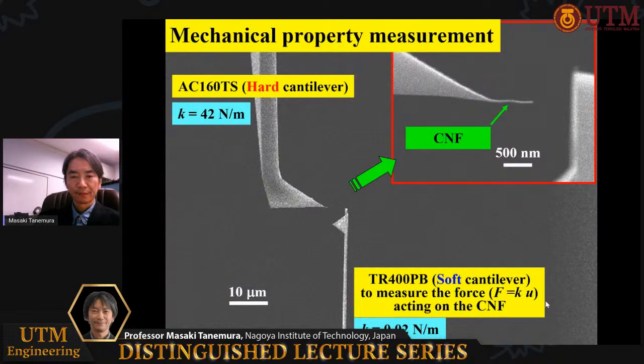This is a setup for the measurement of the mechanical property. Here is a carbon nanofiber grown on the AFM cantilever. This is also a cantilever, but a very soft cantilever to measure the force acting on the carbon nanofiber. This is the force constant of this soft cantilever. We can calculate the force acting on the carbon nanofiber from the displacement U of the soft cantilever using the well-known equation F equals KU.